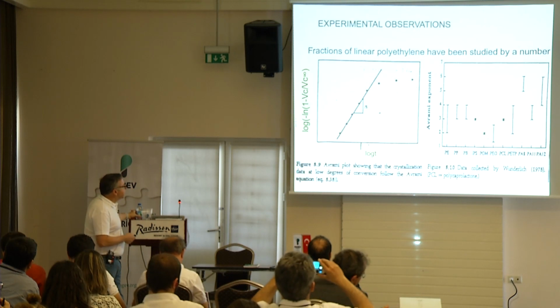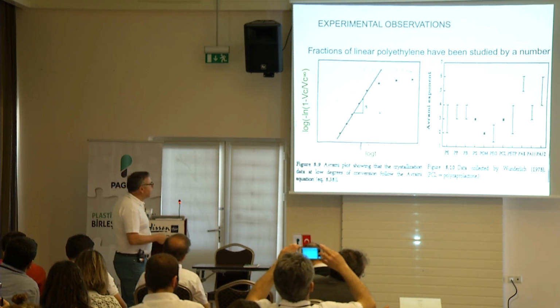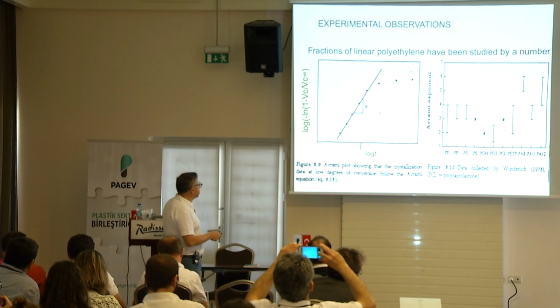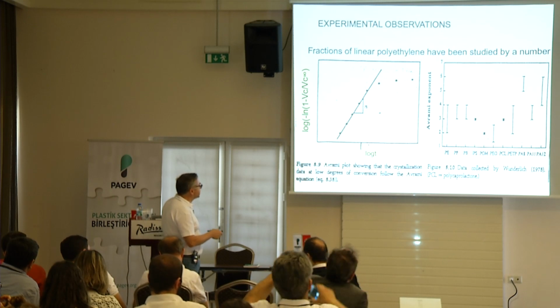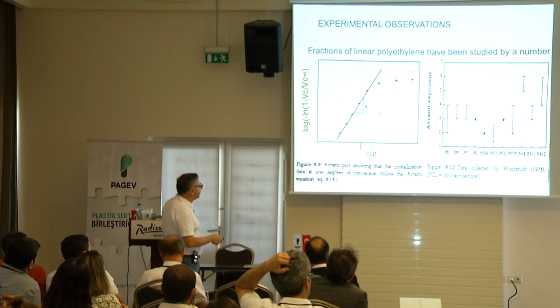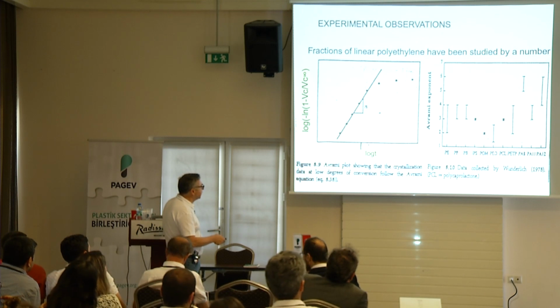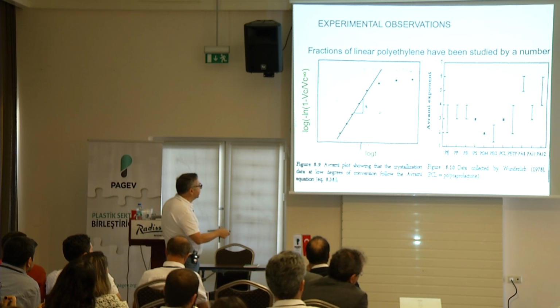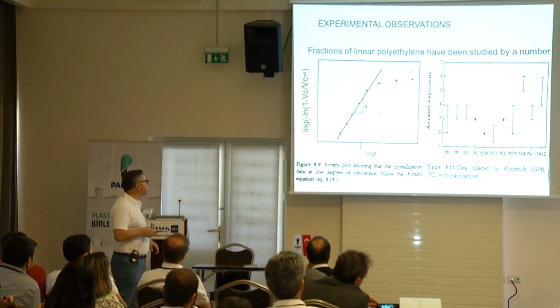All right, some experimental observations, typical numbers that have been reported. Here is the Avrami exponent for polyethylene and polypropylene. These are the ranges that people have. Nylons, anywhere from 2 to 6. This is the space that is covered from the experiments.